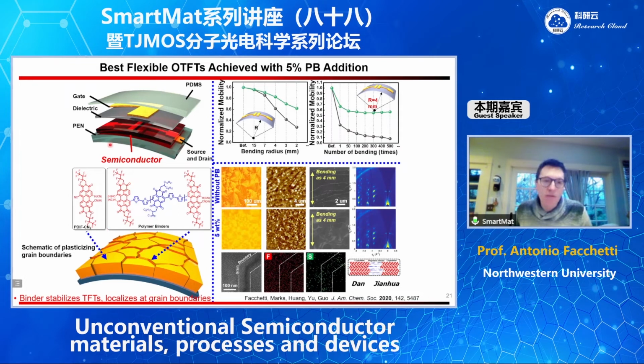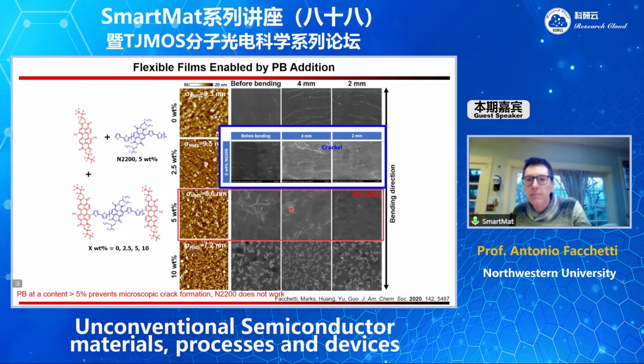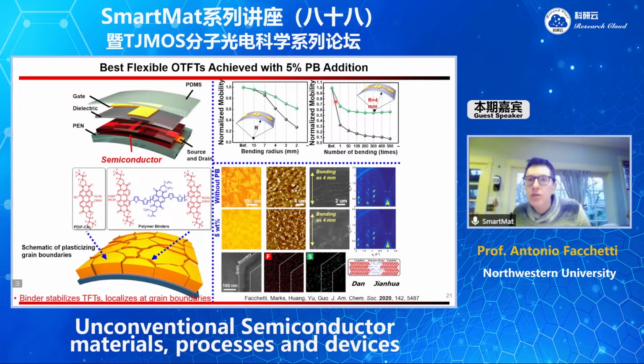And this translates to devices which, when you bend them, just look at these two plots. The black plot, if you bend these devices multiple times, it cracks and then it continues to degrade the performance. Instead, if you add about 5% of the additive, at the beginning there is some cracks forming, and maybe you actually see a little crack here. So there is a small degradation at the beginning, but after this first crack forms, there is no additional crack propagating because there is plasticization of the grain boundaries.